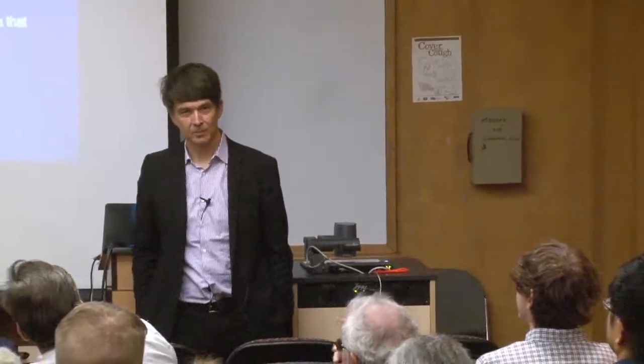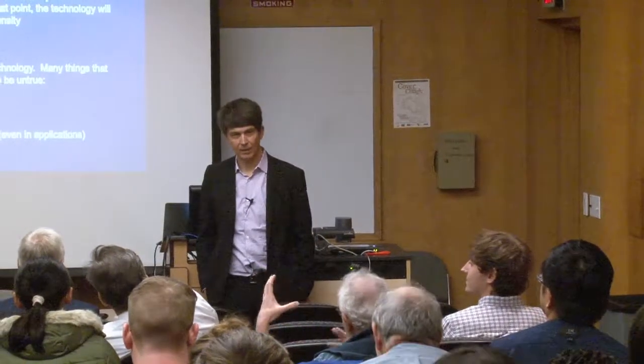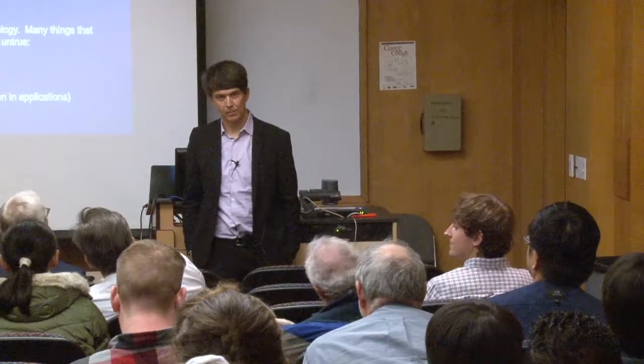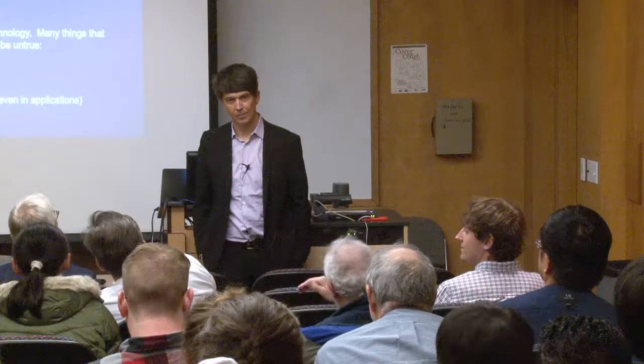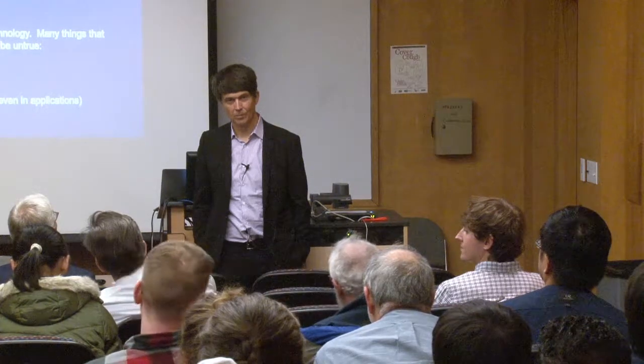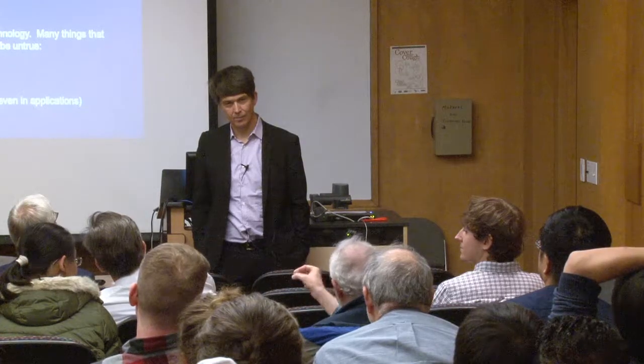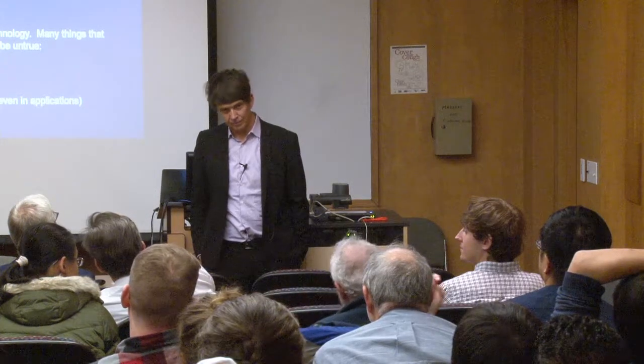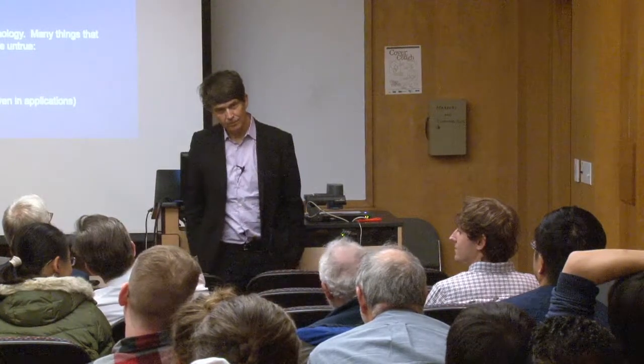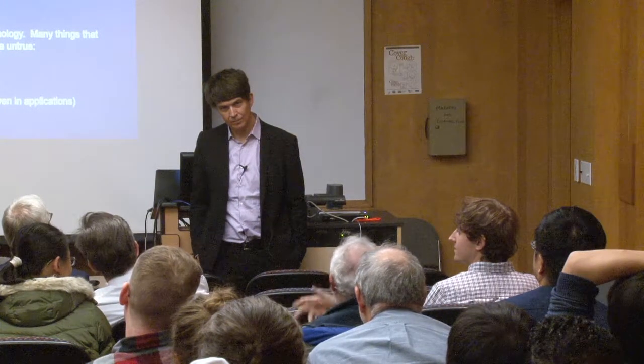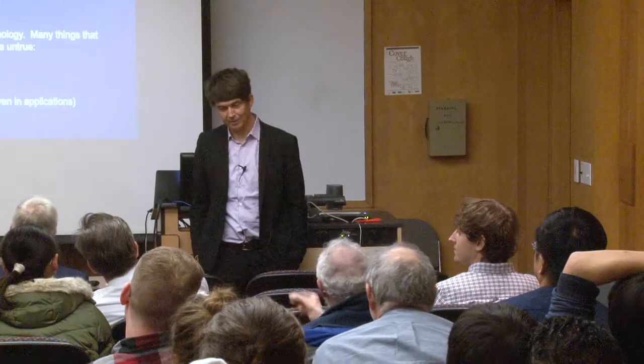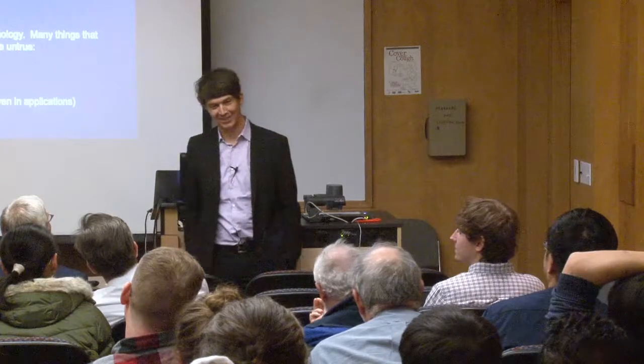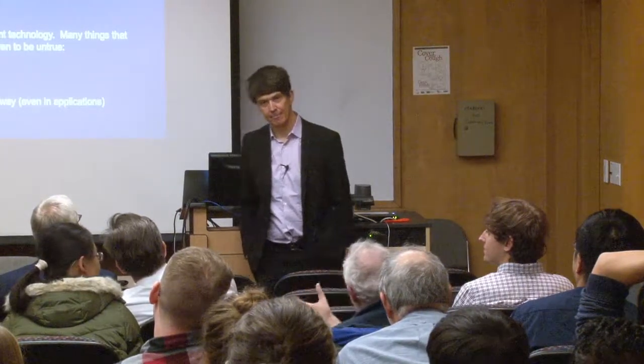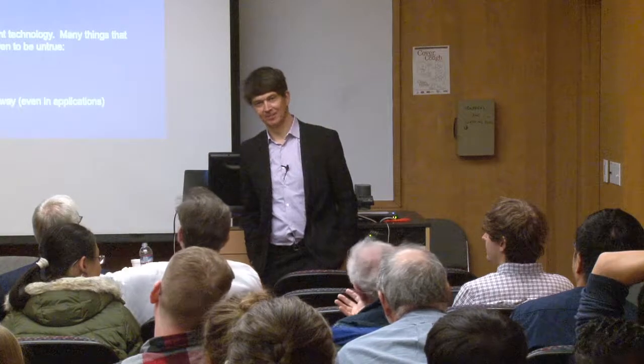I have two quick points. I like your quote at the end about fundamental understanding. I find it interesting how you think of all these structures as rocksalt based, but in the beginning you also said they are layered, right? The way I think of lithium cobalt oxide is that the cobalt oxide layer is negative and the lithium is positive. Lithium gives its electrons, so the cobalt is happy. But now you take the lithium away, and the cobalt isn't happy anymore because it becomes a metallic layer, with p-type dopants. So how much of the lithium can you take out without making the cobalt unhappy?